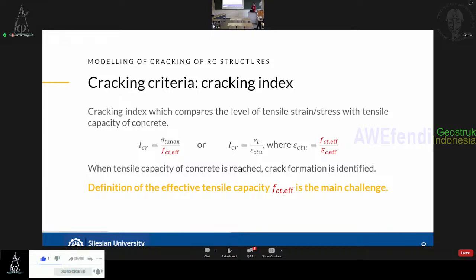And the simplest method to do this is to use the cracking index, or something that we can relate to the cracking index. However, I don't want you to mix it with the thermal cracking index that we have in the JCI guideline. Nevertheless, such a name appears in the literature. But as you can clearly see from the equations which I show, this is a procedure in which, depending on the approach which we use, either stress-based or strain-based, we are relating the tensile strain or tensile stress to the tensile capacity of the element. And I would say that the main challenge in this process is the definition of the effective tensile capacity, so the value of tensile strength where we say that cracking appeared. But I think this problem has been discussed a couple of times today. So this is just to mention the problem.